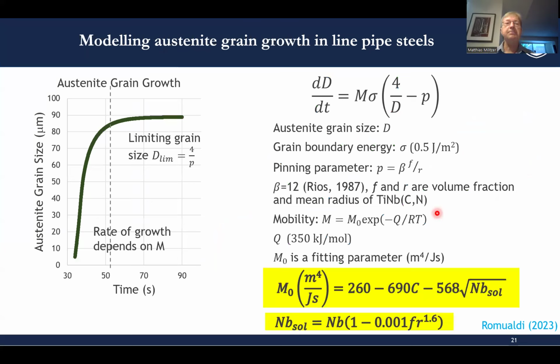Now we can describe this classical grain growth behavior. So the initial portion depends primarily on the mobility of the boundary, the limiting grain size on the presence of the titanium nitrides, very classical grain growth equations being used, where the classical parabolic grain growth is mitigated by this pinning term from the titanium nitrides that is related to the volume fraction of these precipitates at their mean size. And the volume fraction can be determined with CALPHAD databases, and some electron microscopy was done to verify that this limiting grain size is consistent with this approach.